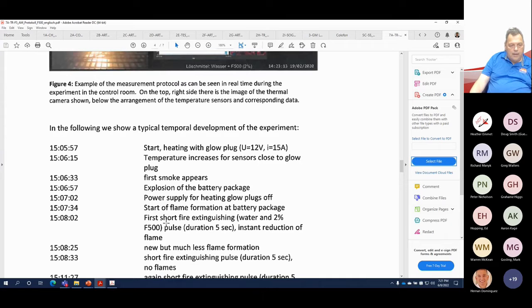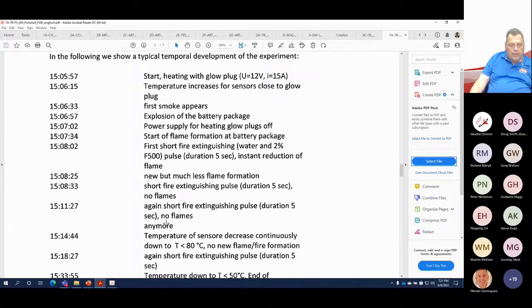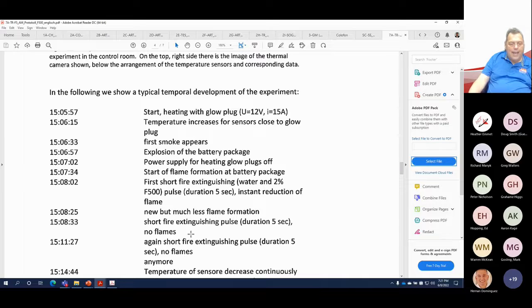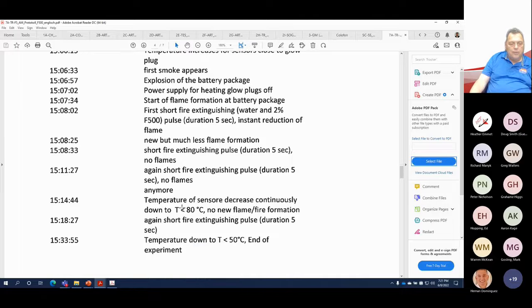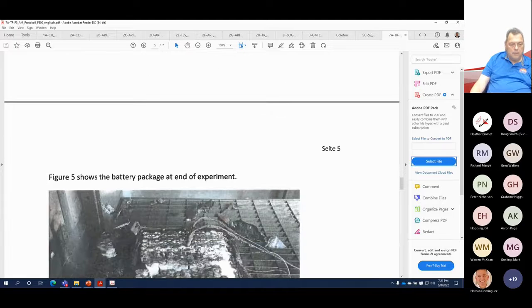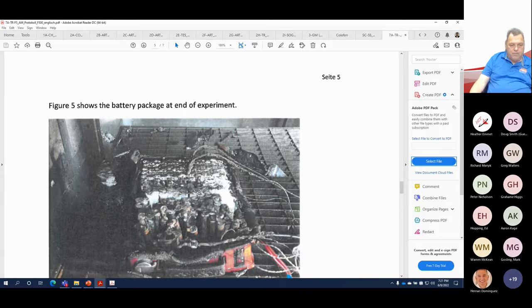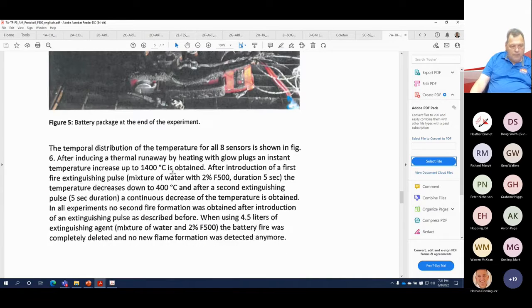So we have gone here from 1400 degrees down to less than 80 with only 3 5-second bursts of F500. And now we're waiting 15 minutes and the temperature is continuing to decline down to 50 C. Here we can see that we've stopped the thermal runaway and the fire propagation to other places.